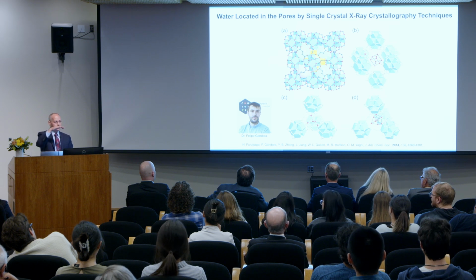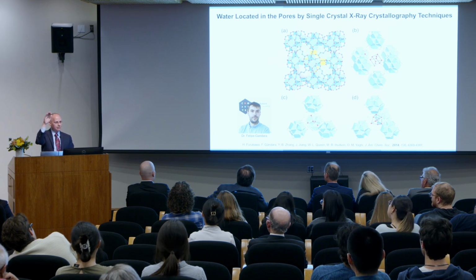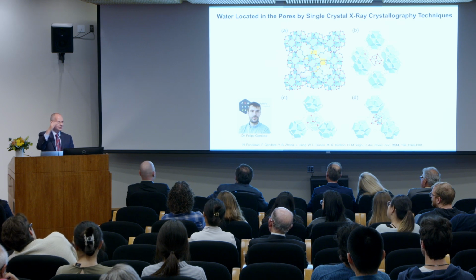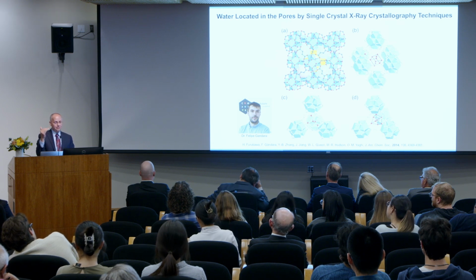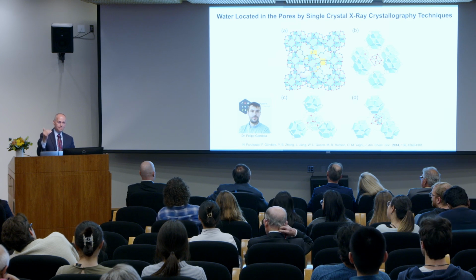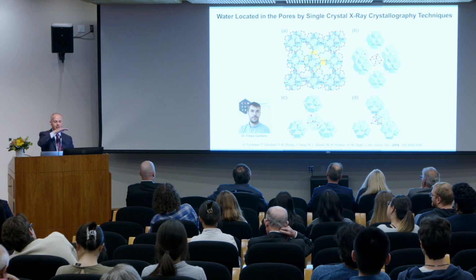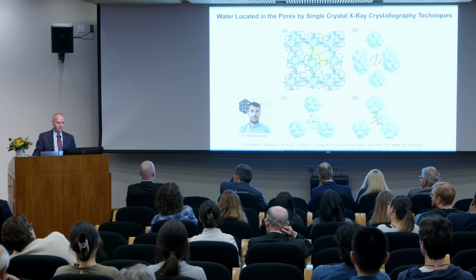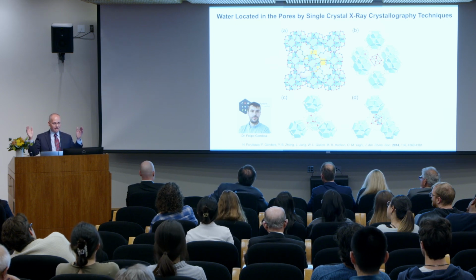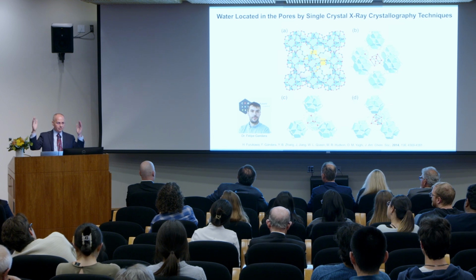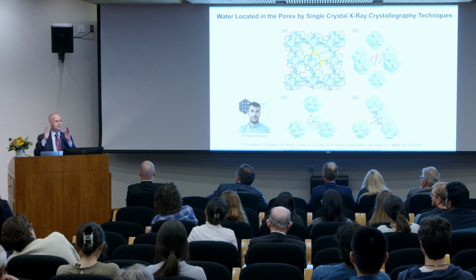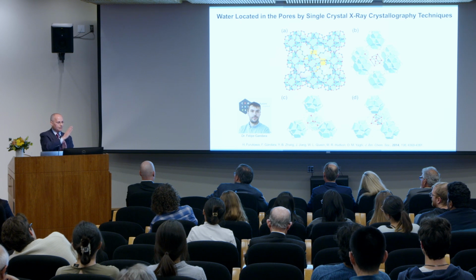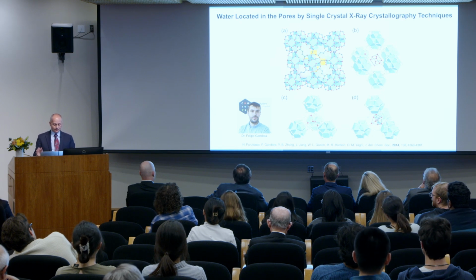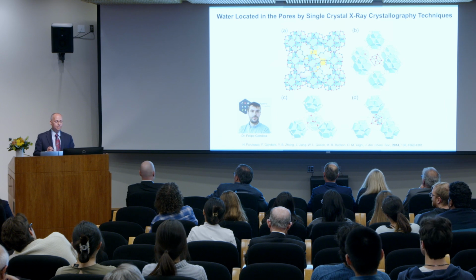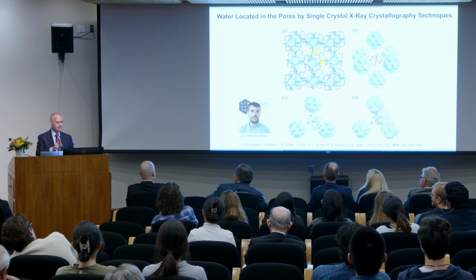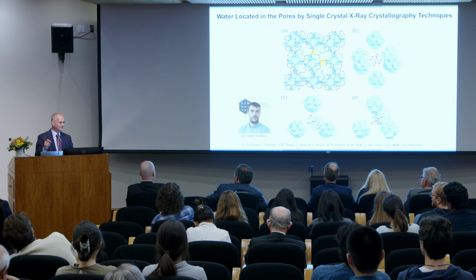And that's why when I showed you the red line, it looks like a cooperative mechanism by which water is binding into the pores. Well, that mechanism is absolutely essential to having a water harvesting material that operates in an efficient manner. If that was a shallow water uptake behavior, then you need a large change of pressure or temperature to get all the water out. But instead, you only need minor perturbation to take the water in and out. So the discovery here was that the first water molecule acts as a seed and never comes out of the MOF.